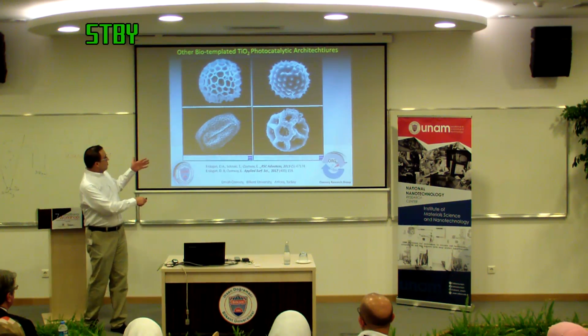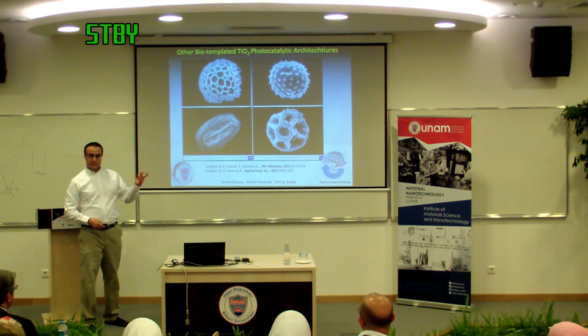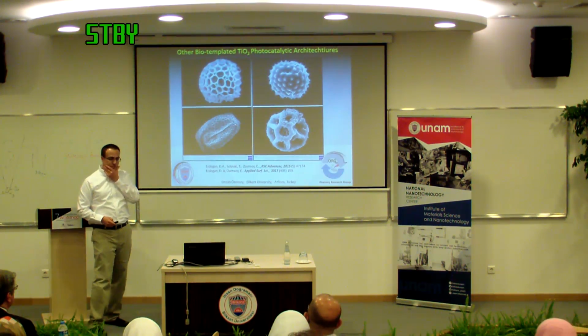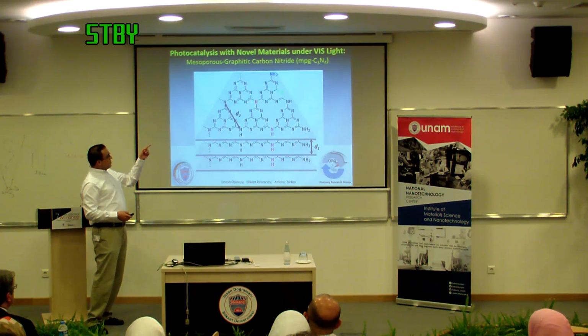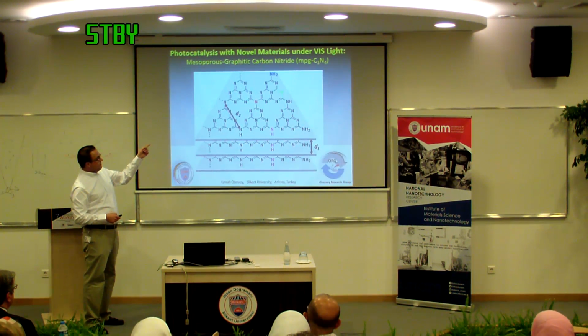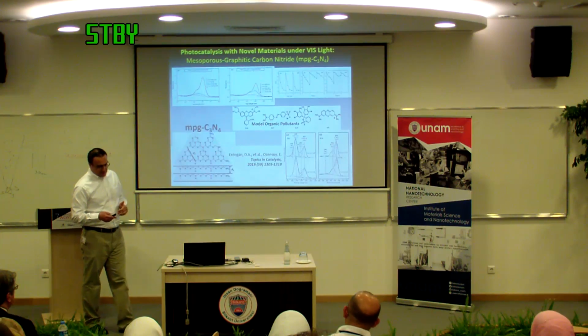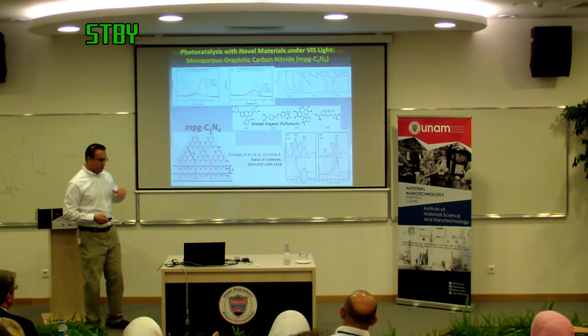And he actually coated all of these materials with titanium and different things, like carbon nitride. So they're interesting. Nanoparticles, gold, silver, and so on and so forth. One possible thing is graphitic carbon nitride, 2.5 eV band gap, 2D material, s-triazine rings, visible active material, very interesting type of material, and we demonstrate that we can actually control the carbon and nitrogen bonding structure over here with different synthesis protocols, and they're active under visible light, and they're reducible. So this is the crucial principle, and we're continuing on this one.